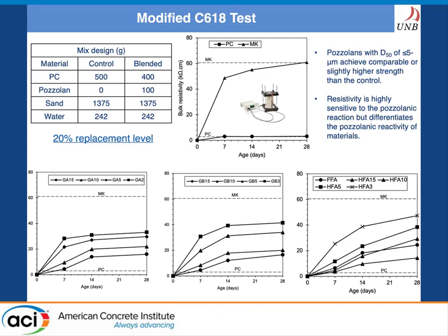The bulk electrical resistivity results from the modified C618 test show that the impact of pozzolanic reactivity on resistivity is more pronounced than on strength. The 100% Portland cement cubes have a bulk resistivity of around 4 kilo-ohm centimeter, whereas mixes with metakaolin reach around 60 — nearly a factor of 15. For all other materials, resistivity increases as particle size decreases, and when the particle size is around 3 microns, electrical resistivity is considerably higher compared to the 15-micron particle size.